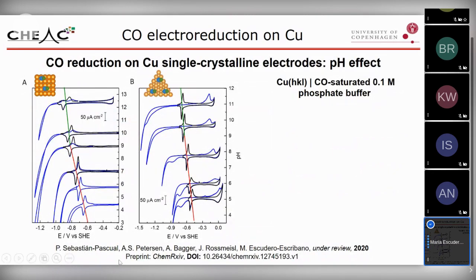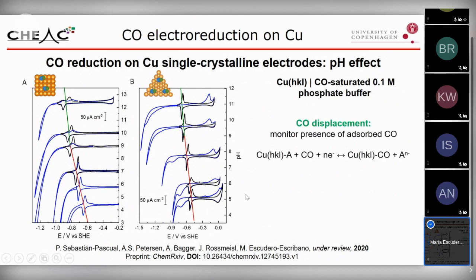We have the preprint published, and these are the CVs of copper 100 and copper 111, all in the presence of CO. This shows the different cyclic voltammograms at all the pHs investigated. These experiments showed the CO displacement. You have the typical phosphate adsorption features, and phosphate is adsorbed very strongly. When you adsorb CO, you are able to displace the anions, the phosphate, and then adsorb the CO. And this is what these features are telling you.